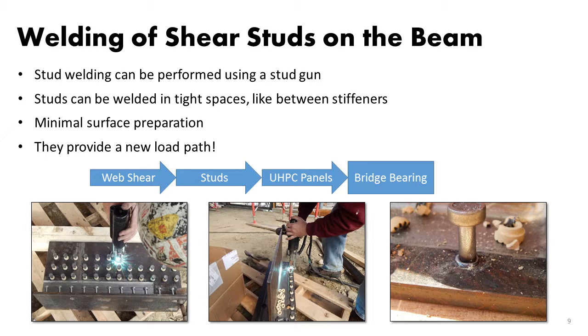So one important component of this detail is studs. And we needed to carefully study the studs and their behavior. So just to give you an idea of how they are welded, we have a stud gun. We don't need to weld individual studs by hand. It's like 20 seconds per stud. I mean, it's very quick. They can weld as many as you want in 1 hour or 2 hours. Minimal surface preparation. The contractor even said, I can weld on the existing paint. We can explore that, but just minimal paint removal. And this is how the final product looks.